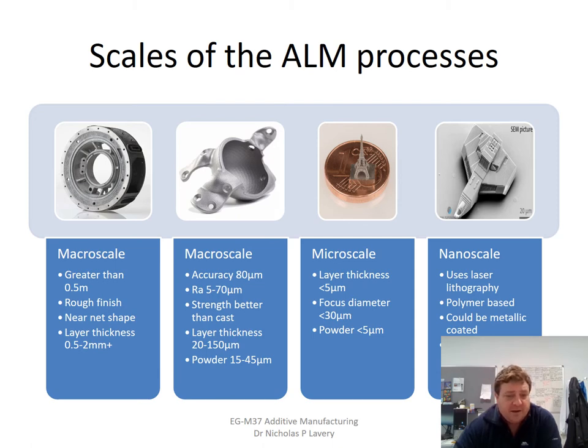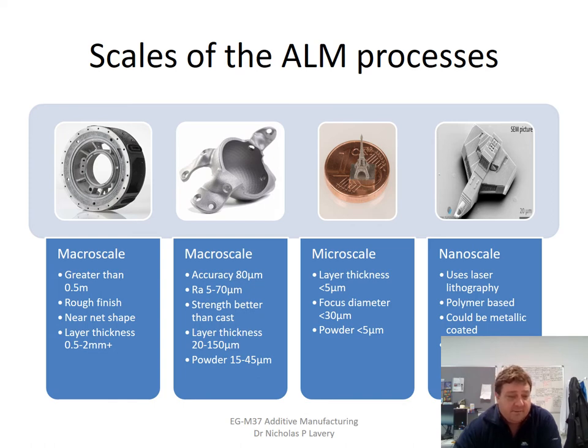On the smaller macro scale, we're talking about parts up to around 250 cubic millimeters — most of the powder bed fusion systems available now. Typically the base plate is around 250 to 500 millimeters squared, with slightly higher accuracy and lower surface roughnesses. Strengths can actually be higher than cast material. Layer thicknesses range from 20 to 150 microns depending on the powder bed system. Powder sizes typically used for additive manufacturing are 15 to 45 microns for powder bed, though electron beam systems tend to use slightly larger powder size distributions.